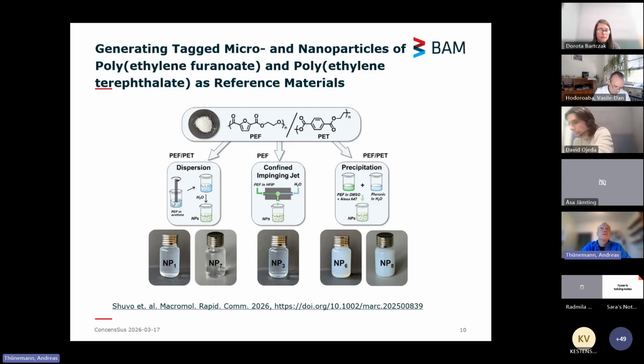Then we use confined impinged jet. This is also a method which produces spherical particles, but you use hexafluoroisopropanol during the synthesis, but the particle preparation goes quite well. And then we use a precipitation method in DMSO, but in this case with the help of a stabilizer, Pluronic, which allows us also to incorporate fluorescence dye, which is well known in cell culture experiments. So PEF and PET are available labeled with these Alexa dyes, and we just published a first publication where we see these labeled nanoparticles in cell culture experiments.